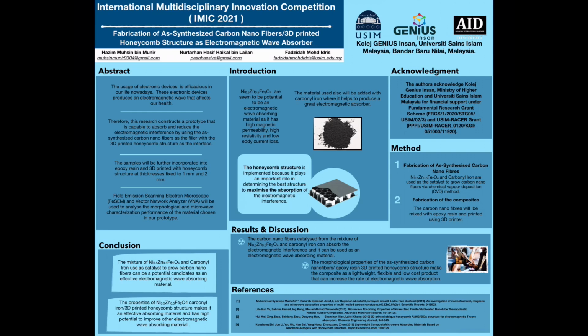After that, we could see the results where the carbon nanofibers catalyzed from the mixture of nickel zinc ferrite and carbonyl iron can absorb the electromagnetic interference, and it can be used as an electromagnetic wave absorbing material. The morphological properties of the as-synthesized carbon nanofibers epoxy resin 3D printed honeycomb structure make the composite a lightweight and flexible low-cost product that can increase the rate of the electromagnetic absorption.